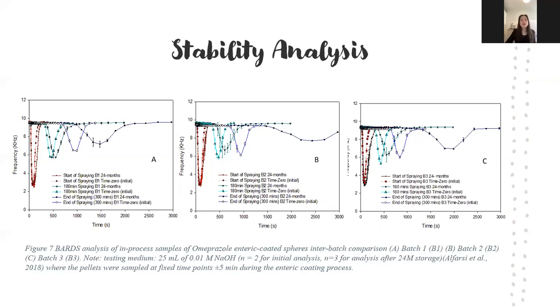So figure 7 shows also a stability analysis for an inter-batch comparison of samples obtained at similar time points during the enteric coated process. So samples were tested initially when received, and also tested 24 months later. So the interbatch variability in the initial analysis shown to be insignificant. However, after 24 months, a change in enteric coating dissolution and breakdown has occurred.